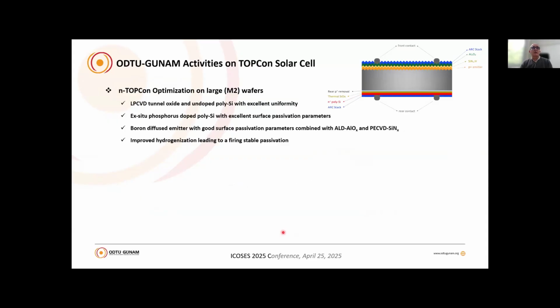What are we doing at GÜNAM? I will later give you very short information about our research center. We have created a quite extensive, comprehensive infrastructure to develop solar cells in Turkey. At the moment, we are focusing on TOPCon solar cells because of the industrial relevance. So far, we have studied the tunnel oxide needed on the backside, this thermal silicon oxide. We have studied phosphorus doping on the backside. We obtained excellent passivations, and the boron diffused emitter on the front side has been quite well produced and also passivated using aluminum oxide and nitride. We have developed our own hydrogenation experiments for this structure.